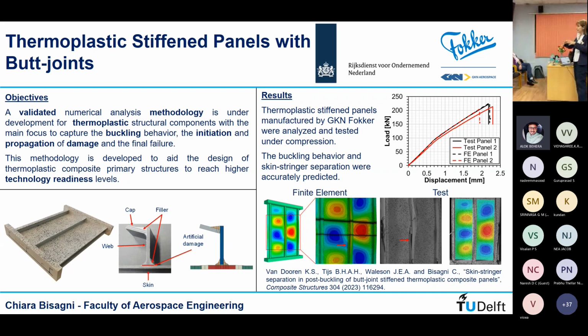But especially, it can be used to join curvature panels. This was a study on flat panels, but we also tested curvature panels, and this can be used to manufacture double curvature panels, and in that case you can tailor the stiffness independently on a level of curvature. So as you can see, in this case we wanted to investigate the buckling phenomena, because of the joint technology, this can be a weak area.